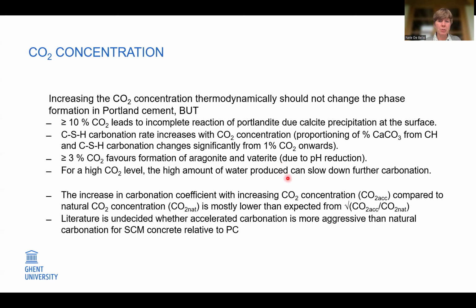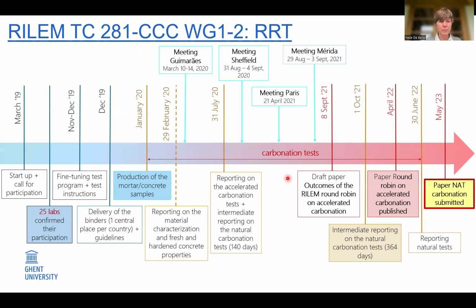Also, at higher CO2 levels, the release of water during the carbonation reaction will go faster. And actually this water in the pores can slow down further carbonation. So normally the increase in carbonation coefficient with the carbon dioxide level is lower than expected from the square root law that we would normally theoretically apply.